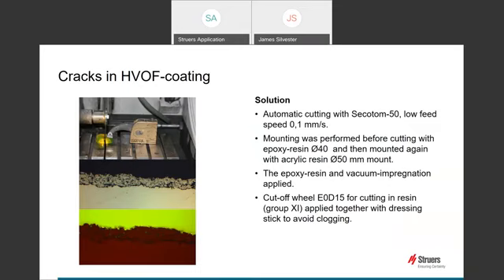During discussions with the customer, it was also found out that cutting was sometimes carried out incorrectly, so the coating was being pulled away from the main body of the material. Education of the operators to ensure coatings are always supported during cutting means that the coating will be on the top surface during a cut of this type, allowing the bulk of the material to support the more brittle properties of the coating.